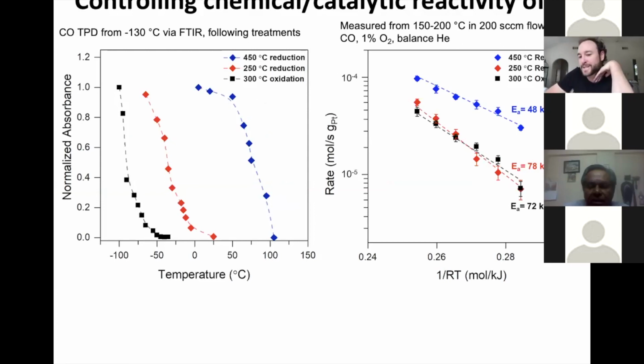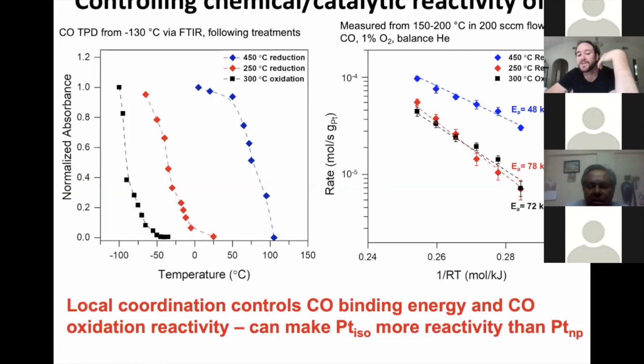If you go measure its catalytic reactivity, again, you see that more neutral species have higher turnover frequencies for CO oxidation than the more oxidic platinum species. And there's all sorts of details here, but what this tells us is that the local coordination environment controls the CO bonding and CO oxidation reactivity. So we can tune this environment and we can make these atomically dispersed species more or less reactive as you tune this, and this is all dictated by the environmental conditions.